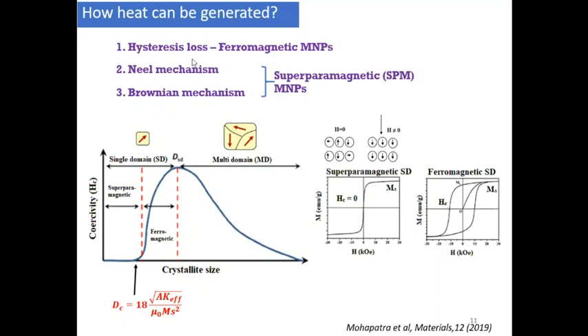The Neel mechanism is based on the relaxation of the magnetic moments. When you apply the field and switch off the field, the magnetic moment relaxes and generates power or heat. And there is the Brownian mechanism, because the nanoparticles are in colloidal suspension, and during the movement of the nanoparticles, their physical motion gives you the Brownian mechanism. These happen in superparamagnetic materials.